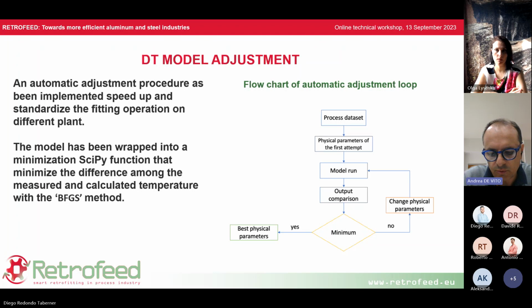To automatize, so to speed up and to standardize the adjustment procedures, a new routine has been developed to automatize these procedures. So the model has been wrapped into a minimization function that minimizes the difference between the measured temperatures coming from the plant and the temperature predicted by the model. This function minimizes this mathematical difference by changing iteratively the physical exchange parameters used as tuning parameters.